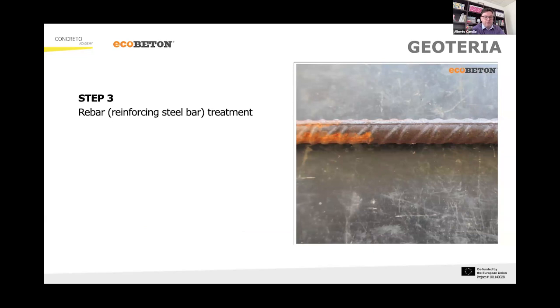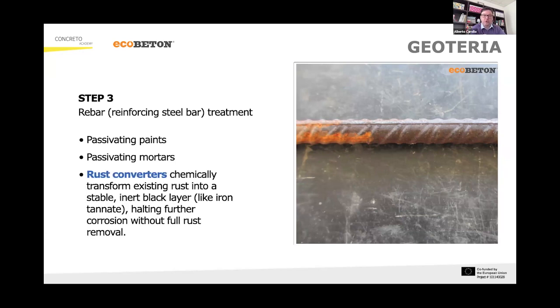Then you have to take care of rebar, because of course rebar are probably already rusted when you meet them. So you got basically three strategies. The first one is passivating the rebar with paints. It's a very old technique. Nowadays, almost all the producers prefer to use passivating mortars, so mortars that already have this passivating stuff inside the mix. What we prefer in any case is to use rust converters, so to transform the existing rust into a stable layer, so no further corrosion will go on it.